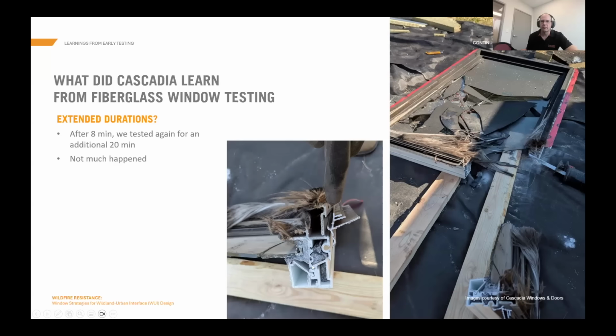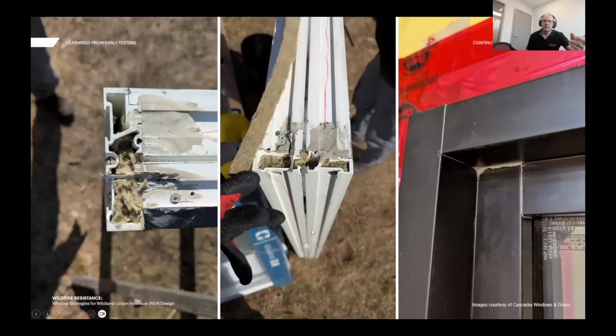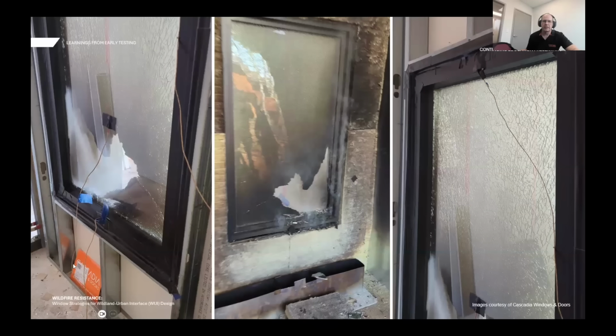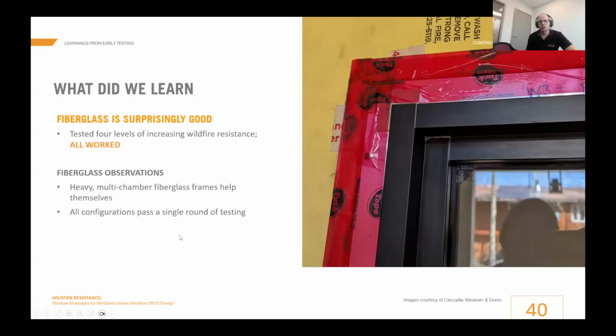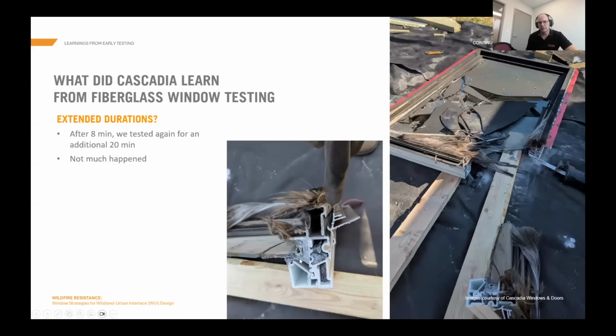I'm going to go a few slides back. I remember walking around in the test hut here, at the 7-minute mark where the fire had been screaming away for 7 minutes, and putting my hand on the window frame. And the window frame's totally fine. It's a little bit warm, obviously, but it's not hot to the touch. It's properly warm. So we learned that the inner half of the frame that's connected to the glass and connected to the wall, the building, is protected by the fact that the frames are deep and multi-chambered.